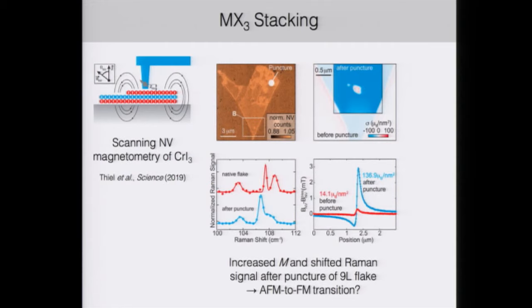So this work, scanning NV magnetometry by Patrick Maletinsky's group, accidentally punctured a 9-layer flake of chromium iodide, but fortunately they were able to get the signal before and after the puncture, and they noticed that the magnetic signal greatly increased after puncturing, and there was also a shift in the Raman signal. So they attribute this to relaxing locally the crystal to a different phase and then inducing this AFM to FM transition. So presumably this is due to the stacking change from the monoclinic to rhombohedral.